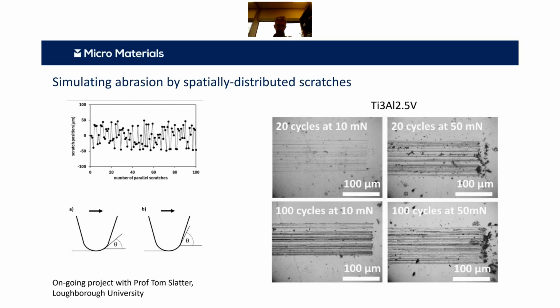And again, on the bottom two, if we're comparing, say, 10 millinewtons at 20 cycles and 100 cycles, you can see it's not just the load. You can run that on, and you're getting that transition to these more damaging regimes. You get load dependent deformation. You also get number of cycles dependent deformation. You get this debris. So we've had some interesting results, particularly for additive manufactured applications that we're working on. It's quite a nice correlation between performance in this test and performance in the G65 abrasive test.